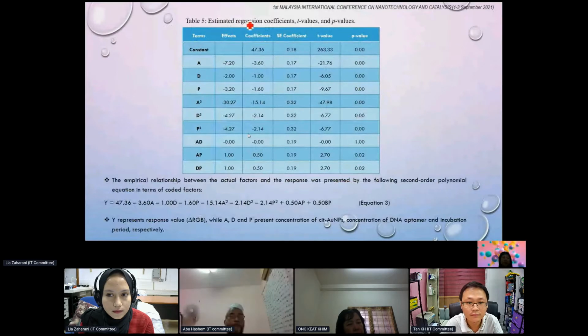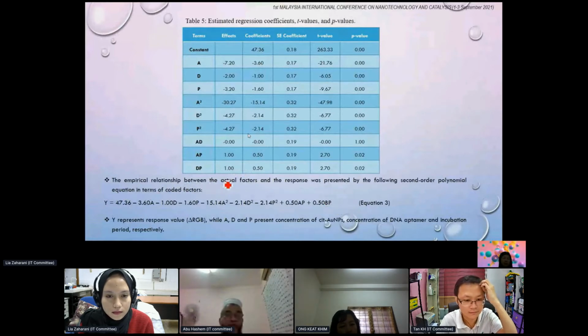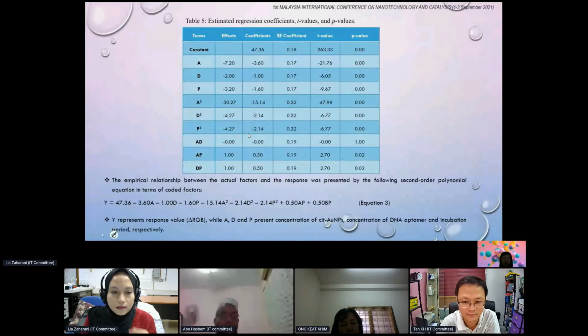Table 5 shows the estimated regression coefficient, T values and P values. So this coefficient will be substituted in equation 1 to get this equation 3. This equation 3 shows the empirical relationship between the actual factors and the response, where Y shows the response value of delta RGB, and A, D, and P show the concentration of citrate AuNP, concentration of DNA aptamer, and incubation period respectively.